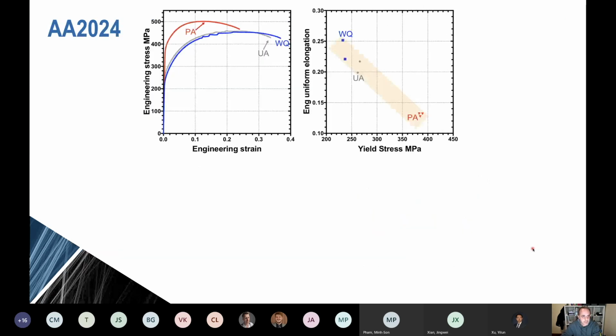So I'll just show you one example so I can get into some more interesting new stuff. This is for the 2024, an aluminium copper magnesium alloy. What I'm showing you here is 3 stress strain curves that we would have from the traditional material. The blue is the water quenched. So that is the stress strain curve from the material in the solution treated and quenched state, all of the solute left in solid solution.